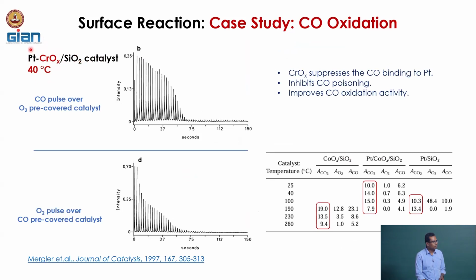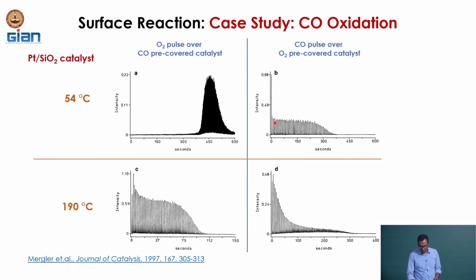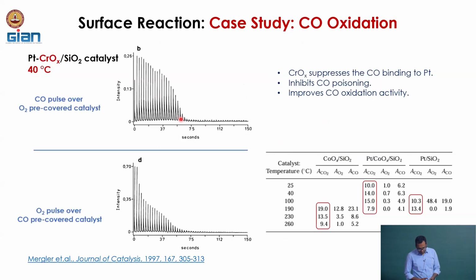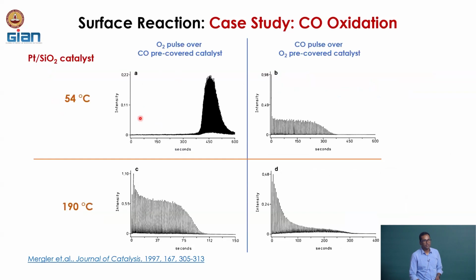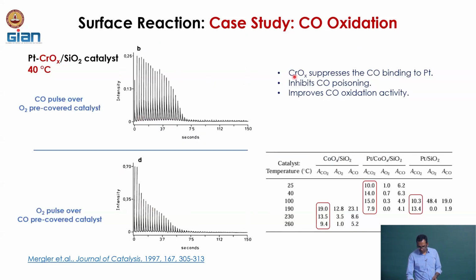But now, even if we are at 40 degrees Celsius, I have the oxygen pre-covered surface, we are pulsing CO, definitely we are seeing CO2 because it is an oxygen pre-covered surface, and oxygen covering of platinum does not hamper CO adsorption. That is what we saw here, right. Once we have the oxygen pre-covered, it does not hamper CO adsorption, but once we have the CO adsorbed, it actually hampers the oxygen adsorption. But in the other case, when the surface is pre-covered with CO and now I am giving oxygen, I am still able to see product even at a much lower temperature, which I was not able to see in this case. Okay. So what is the conclusion?